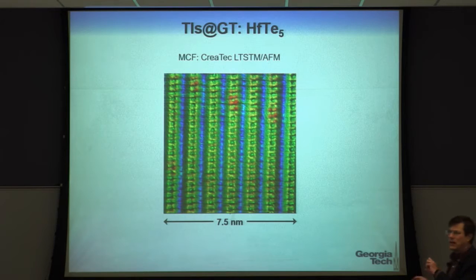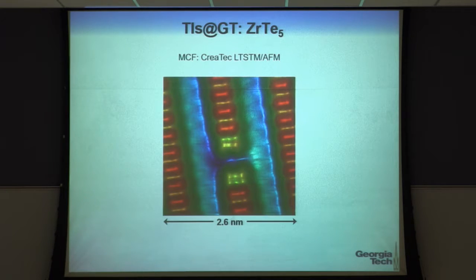The graphene that I showed you, largely the height scales that we're dealing with were tens of picometers. I'll remind you that the Bohr radius is 50 picometers, right? So these vertical scales are typically on the scale of a hydrogen atom or less. This is zirconium pentatelluride. We're trying to compare these things to find out whether on one we have a three-dimensional topological insulator, and the other we might have just sheets of two-dimensional topological insulators. Here's the image of a defect in the material. These results are due to Di Chen, who works for Zhigang Zhang and myself.